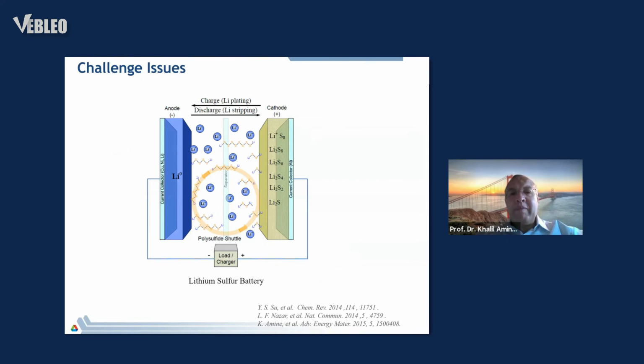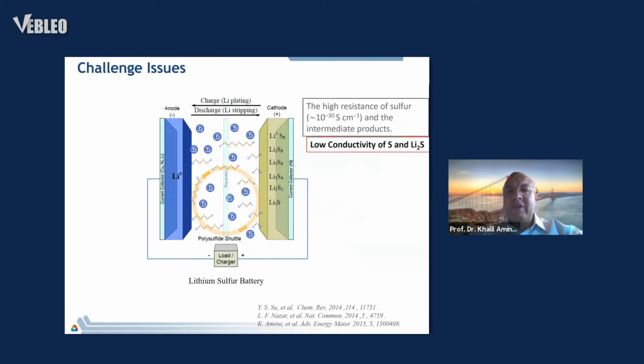The first problem is actually conductivity. Sulfur is insulating. So obviously you need conductivity to allow electrons to move in and out. And so the majority of the scientists have been mostly focusing on incorporating sulfur in carbon. The good news is sulfur can melt at about 100 degrees C, so it's easy to melt it and incorporate it in a porous carbon matrix.